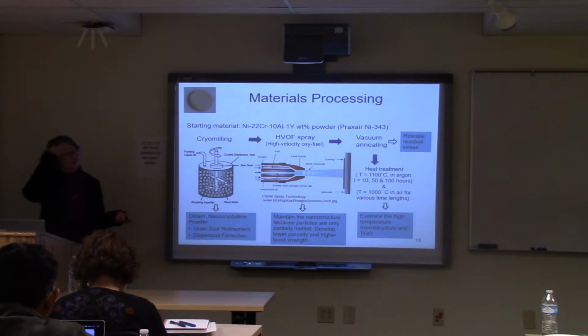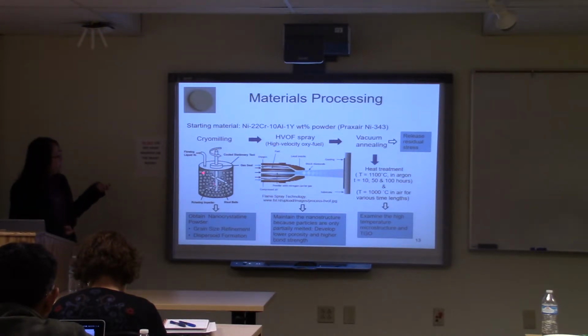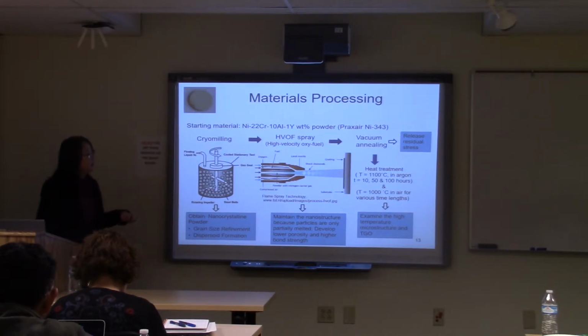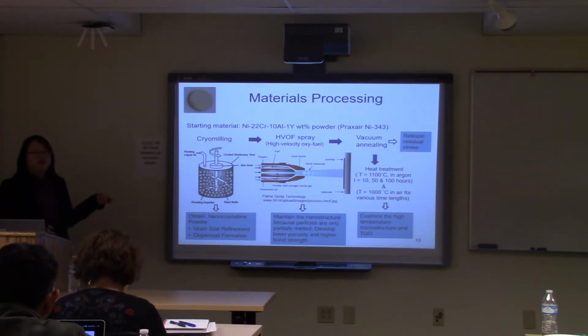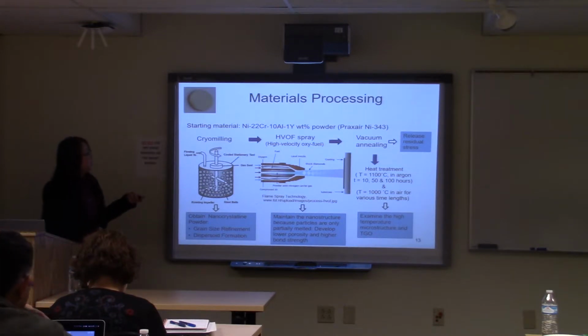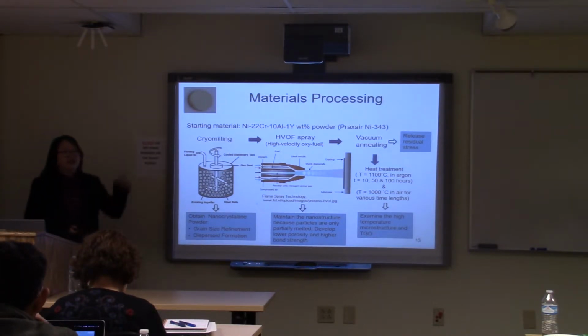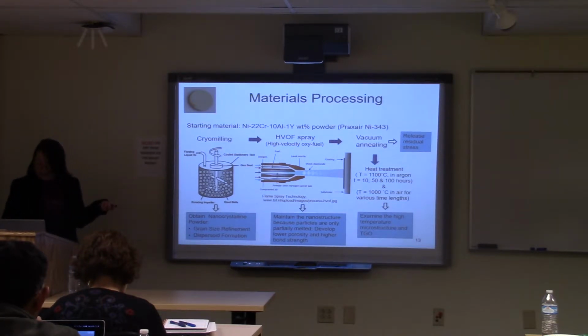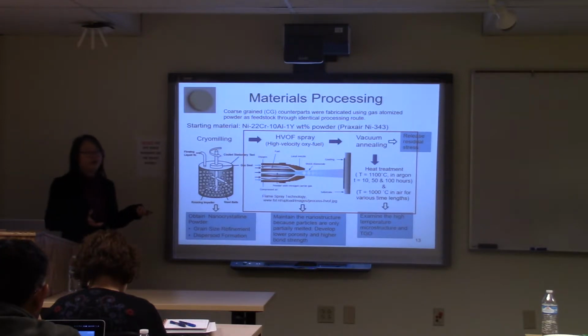So first, I needed to make a lot of materials using cryogenic ball milling, and then we used a technique called high velocity oxyfuel spraying to deposit those powders into coatings. Then we applied some post heat treatment to reduce the residual stress. This is an example of the coupons, including both the substrate and the coating on top. To investigate the mechanism, I also made a lot of conventional materials using identical processing but without cryomilling, using gas atomized coarse grain powders as the feedstock.